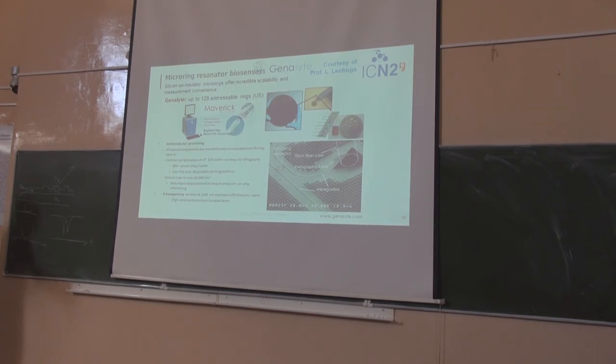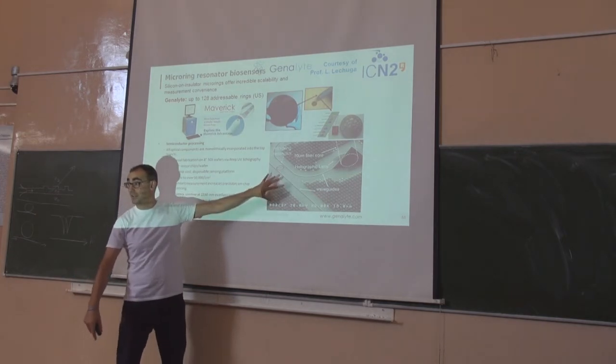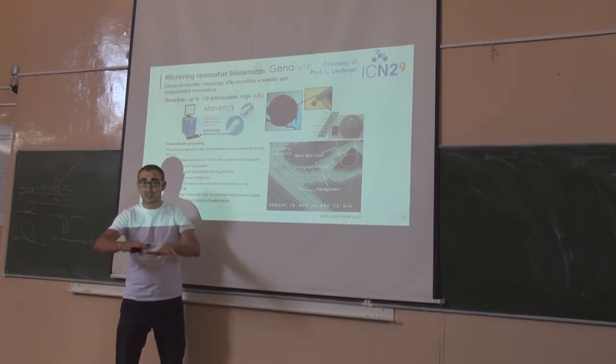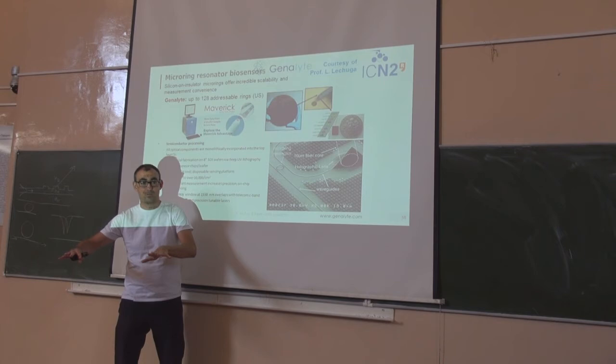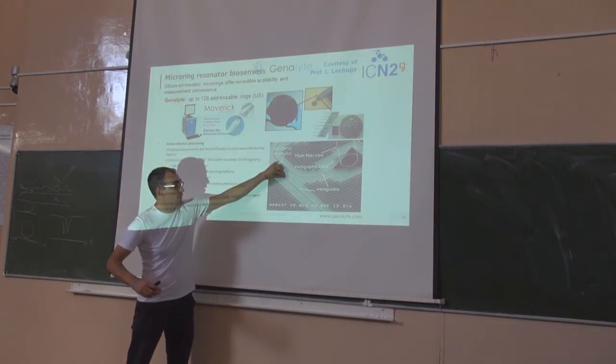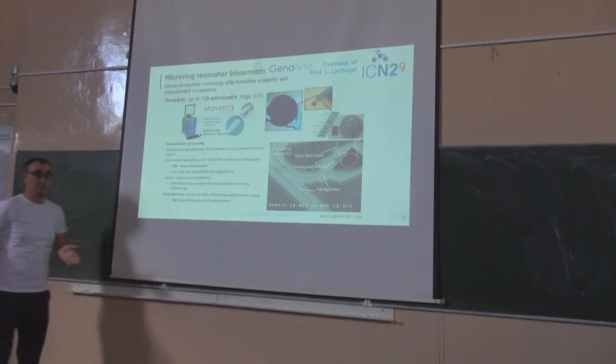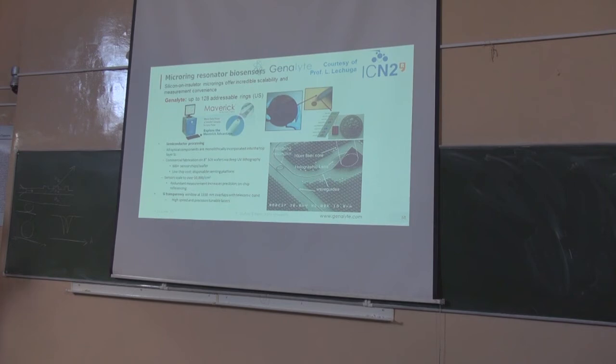So actually, to compensate, you put dummy structures to maintain the density uniform on all the wafer. So you guarantee that the etching gives you this width here and the same width where there are more motifs, more waveguides together. So this is a technique to control the etching.